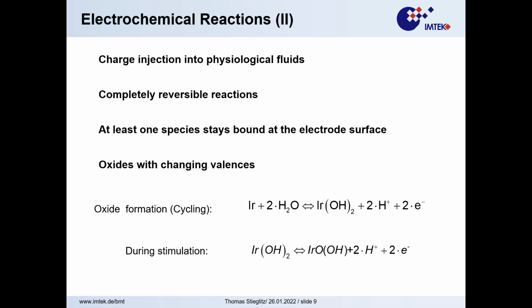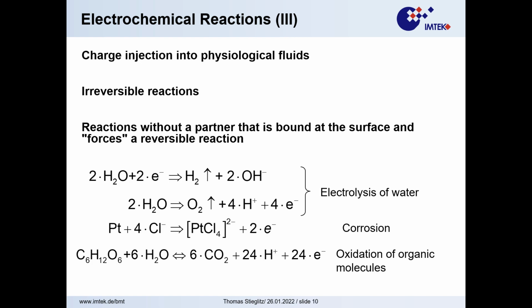What really happens in those thin film metals under stimulation? Do we see it? Are there certain effects on that? And what can we do on that? And if we do something really wrong, then we are out of the water window. That means we generate hydrogen gas, we generate oxygen gas. We might generate platinum tetrachloride. This is a really mean thing that's dissolvable. And it increases the surface of the platinum electrodes.